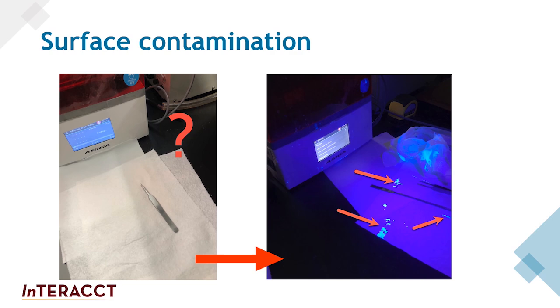The paper towel, bench surface, and tweezers in the picture on the left look clean. But shown under blacklight, we can see several hot spots of contamination. Unfortunately, detection using the blacklight is not a permanent or fully effective detection method because not all resins have fluorescing additives mixed in. That we can see it under blacklight here is because of the additive, not the resin itself.